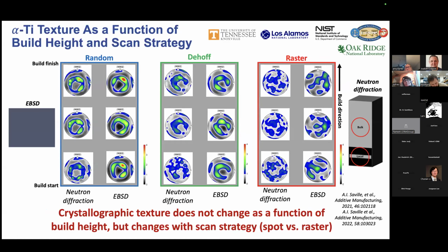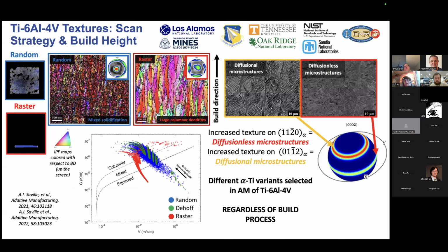And early on in this work, we did some neutron diffraction, sort of up the build height, that allowed us to compare and contrast the textures we got for these different kinds of processing pathways that we used. And we tended to find that as we go up the build height, we don't see big changes in texture, but we do see texture changes when we change from a raster to a spot melt scan strategy, just as an example. We then coupled this with large scale electron backscatter diffraction as well.